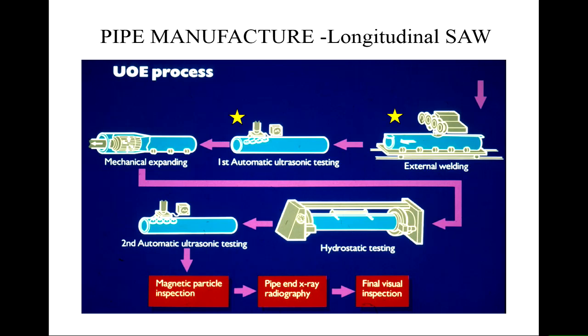So usually we do an automatic ultrasonic test to verify the quality of the weld, because we're then going to apply a mechanical stress to the system. And what we're doing is the E part of the process. We're mechanically expanding the pipe. And what this does is it plastically deforms the pipe, and it will relieve the residual stresses in the longitudinal weld, and it will ensure that the ovality of the pipe due to the welding process is removed. So the expansion is a critical part.